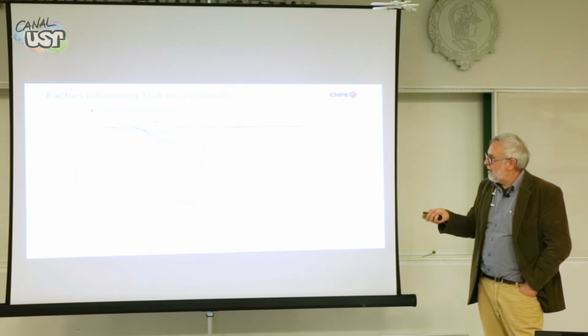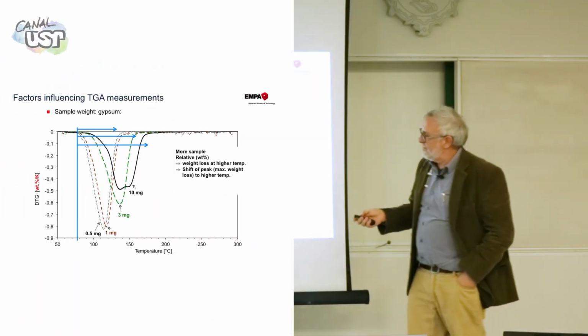And we can go to 10 milligrams, but then the peaks get wider and you lose sensitivity for peaks sometimes. So depending on what you want, you can play around with the sample. What is interesting is the weight loss starts at about the same temperature, but ends at a very different temperature. There is a very simple reason for that. Heat has to diffuse from the oven to inside of the sample. The bigger your sample, the longer it will take for the temperature in the oven to arrive inside the sample. And the oven is moving all the time, so your peak gets wider. That's the reason. And this is, well, we never do that. This is absolute change in temperature.